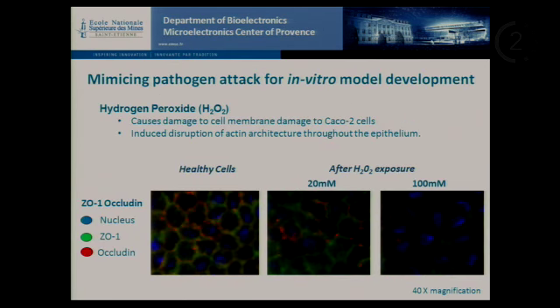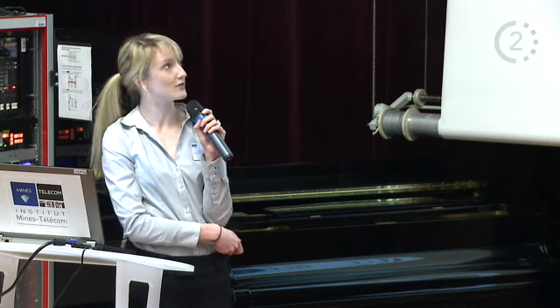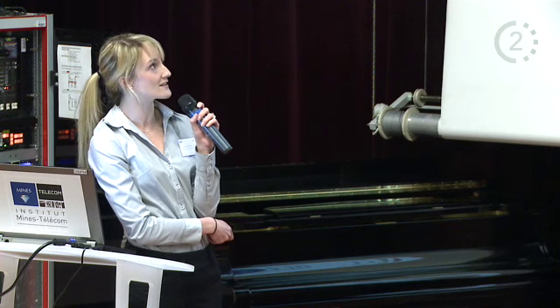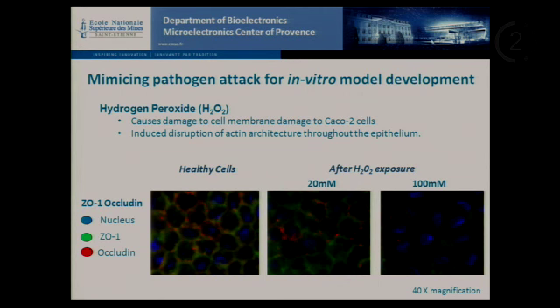So in order to mimic a pathogen attack, we use hydrogen peroxide. It's been shown before that hydrogen peroxide causes damage to the cell membranes, with the damage corresponding to hydrogen peroxide concentration. Shown here are healthy cells compared to cells exposed to 20 millimolar and 100 millimolar hydrogen peroxide. On exposure to the hydrogen peroxide, the tight junction proteins are less organized.